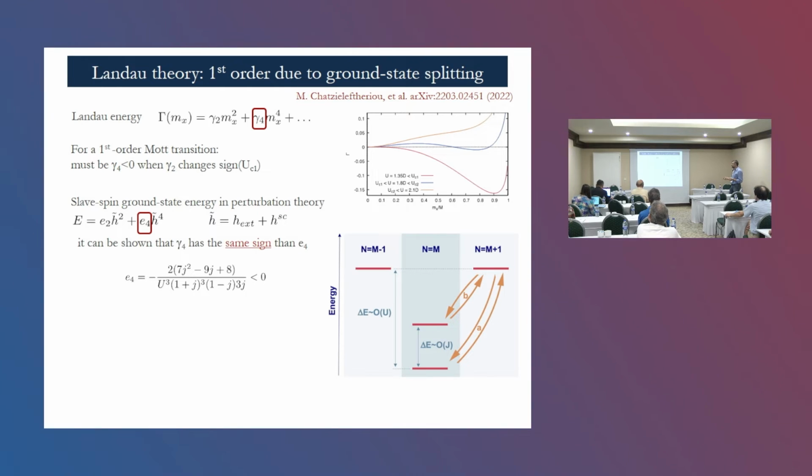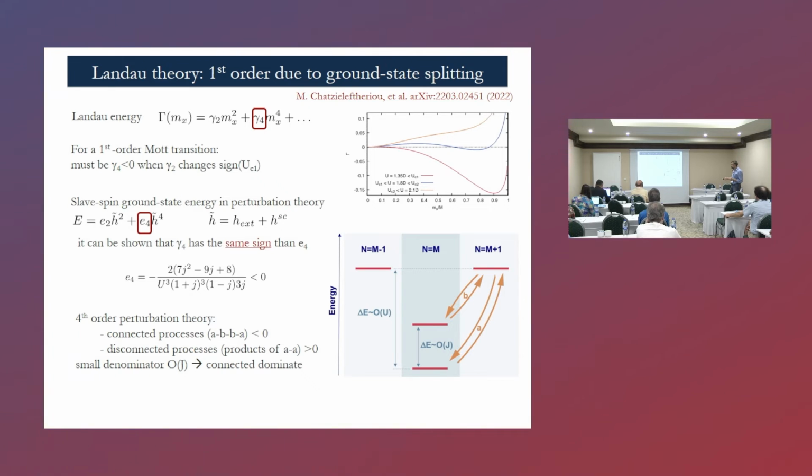I will be short on this, and I just say that we can calculate this, and it's always negative at finite Hund coupling. This is understood in perturbation theory simply from the sketch of the lowest lying atomic states when you have Hund's coupling. You have a triplet state which is low lying and split from the singlet state in the half-filled sector, whereas you have charge excitations to the n+1 and n-1 sectors of charge.